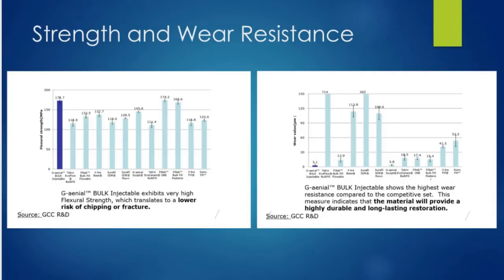When we look at this product, we have to talk about strength and wear resistance because of those smaller particles that are encased in that silane coating, and they're very evenly dispersed, so any small breakdowns at the margin typically are still going to leave you with a very resistant and very polishable surface. So you can take a look at these graphs comparing to many of the other materials that are out there with a lower risk of chipping or fracture, also providing a very high and durable restoration.